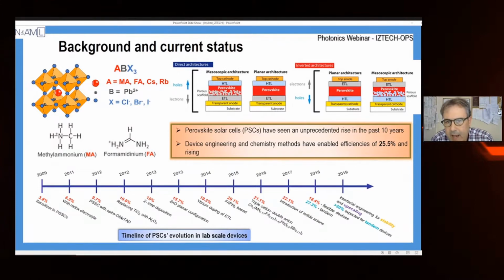What are now the basic architectures of this kind of solar cells? I have on the left the direct architecture and the inverted on the right, which means that we have these two basic structures. As concerns the direct architecture, we have a conductive substrate like FTO. We have an electron transport layer here, which can also be a mesoporous semiconductor like titanium dioxide. This is a nanostructure, a mesoporous structure. And then we have the perovskite, a hole transport layer on the top, and finally the cell is completed with the top electrode, usually made of noble metals like gold or silver.